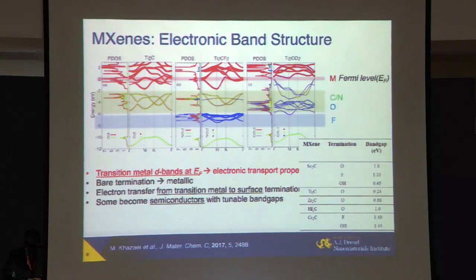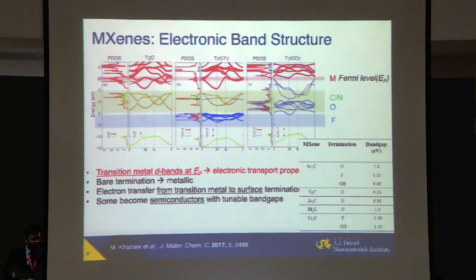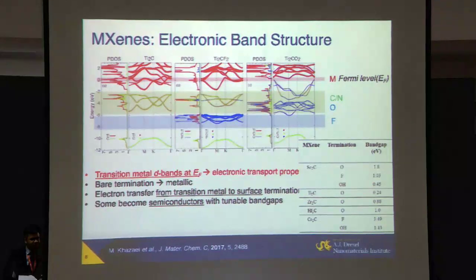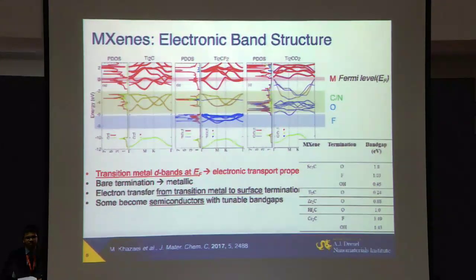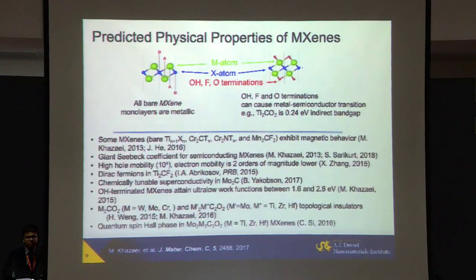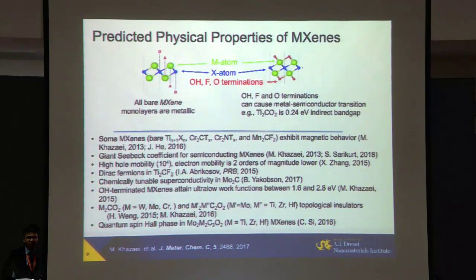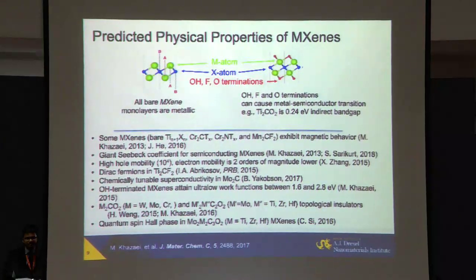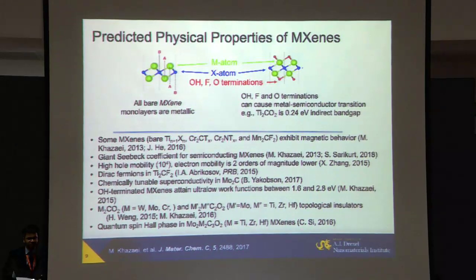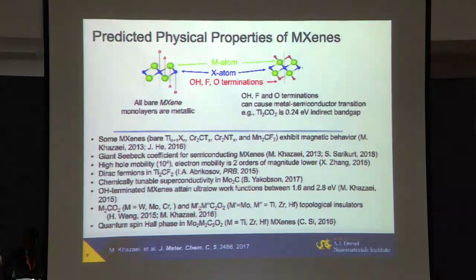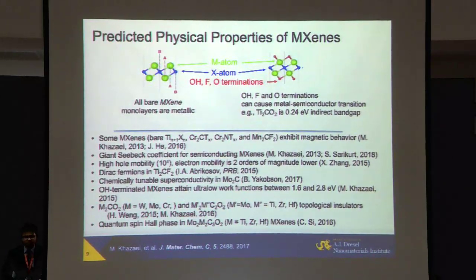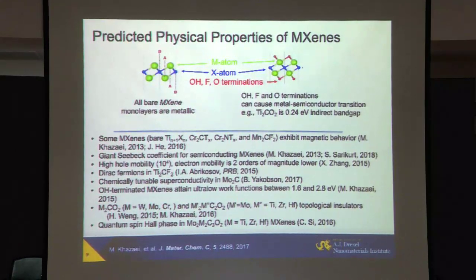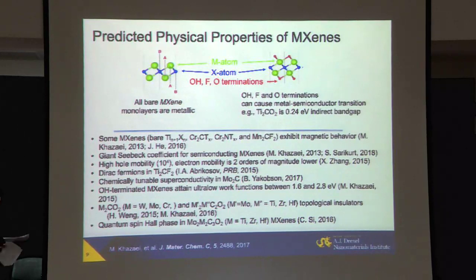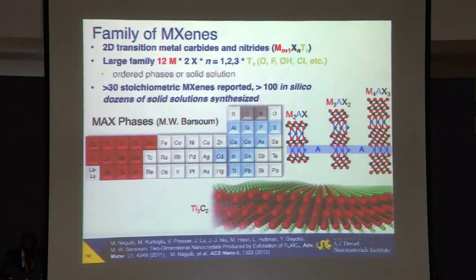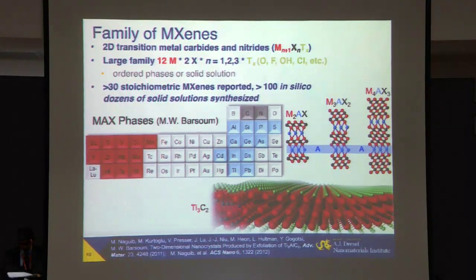So this is what I mean by materials with tunable band structure. Some of the MXenes in this table have actually been predicted to be semiconductors, but they have not been much studied yet because there are plenty of semiconducting materials available in 2D. Still, I'm pretty sure we'll find some interesting properties here. So there have been many other properties predicted. Magnetic MXenes, we're exploring two-dimensional magnetism now in MXenes. Giant Seebeck coefficient means a potentially useful thermoelectric material among semiconductors. Dirac fermions have been predicted in Ti2C terminated with fluorine, like in the band structure of graphene. Ultra-low work function, actually, work function tuning is already used in perovskite solar cells. And topological insulators, many, many others here.